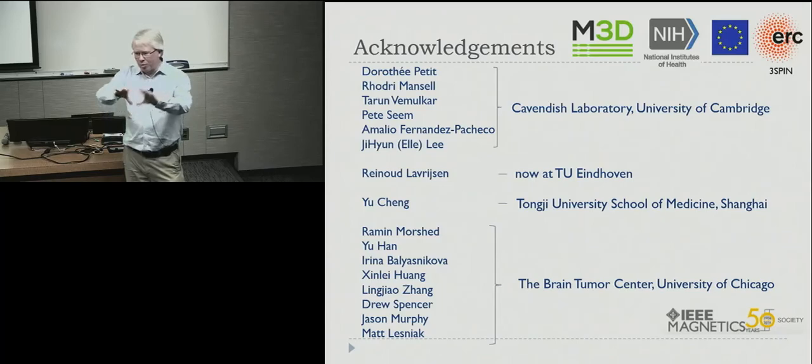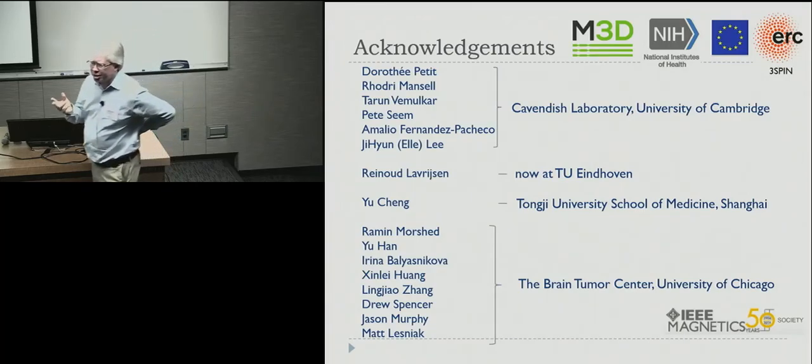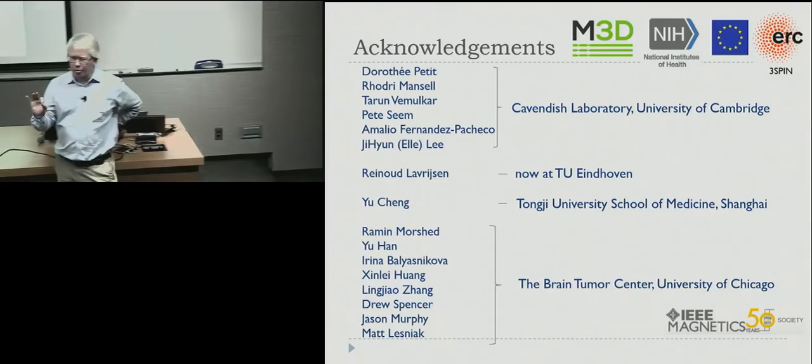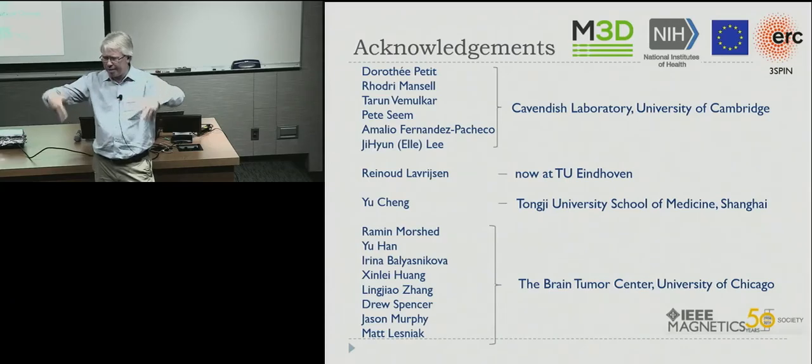The reason the domain walls go out in a smooth circular fashion, and the walls themselves are so smooth, is largely because of the boron. So the boron breaks the crystal structure and makes the cobalt-iron-boron amorphous. That stops a lot of the pinning mechanisms that you'd normally get at crystalline defects from doing anything. So if you compare those domain images to what you'd get in cobalt iron, perpendicular cobalt iron, the wall's much more jaggedy and it's much bigger steps.